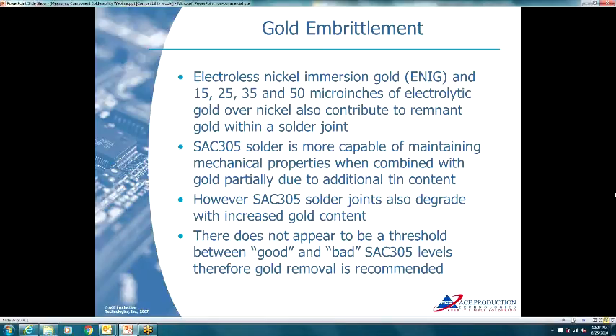However, SAC 305 solder joints do degrade with increased gold content. So there have been all sorts of independent studies done, and the key is, what's the threshold, the maximum amount of gold? Well, as we said, there does not appear to be a threshold. It's not simply acceptable or unacceptable, good and bad. There's been a debate within the industry: is 3% gold by weight the limit? Is it 5%? The agreed-upon decision was 5% gold by weight as the maximum level within a solder joint. However, some people have seen gold embrittlement with gold levels as low as 1 or 2%.